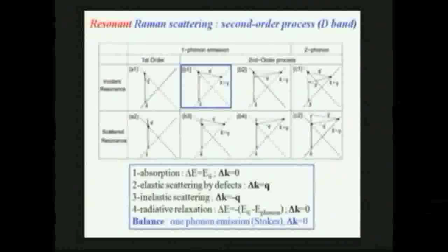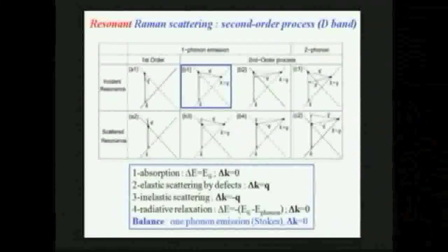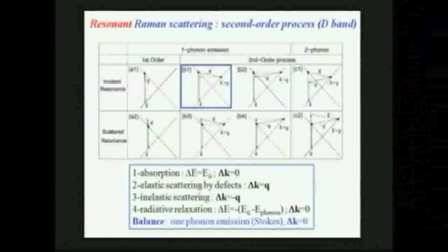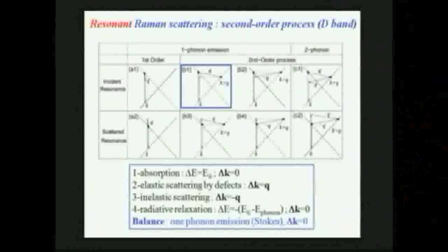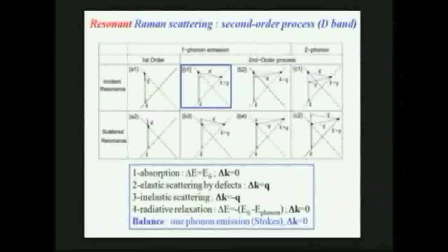So we said that we have resonance when we can absorb light and send one electron of the valence band to one state of the conduction band, one eigenstate of the conduction band. So here, the sketch represents the dispersion curves of the nanotubes that we studied yesterday. So the dispersion curves close to the Fermi energy can be considered as linear.